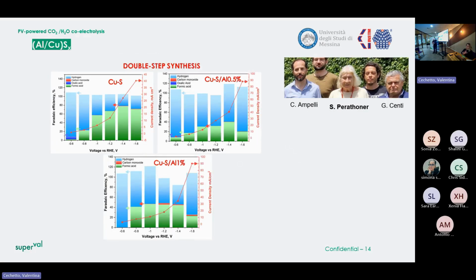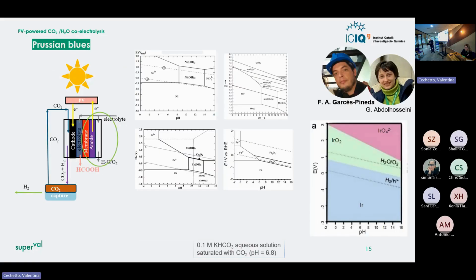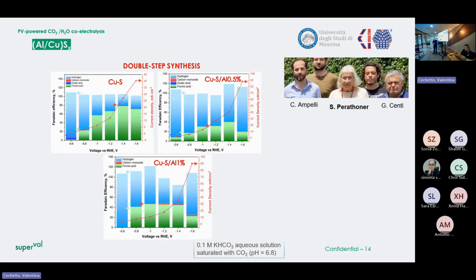And then depending on the synthesis, they can really play with this ratio of materials. One important thing is that for CO2 reduction in electrochemical conditions, you cannot play around much with the water electrolyte. You cannot work in an alkaline pH because the CO2 bubbling is going to reduce the pH. You shouldn't work in a very acidic medium because then hydrogen evolution is going to dominate because it's kinetically faster. So the optimum conditions for CO2 reduction are typically bicarbonate buffer and a pH close to 7.